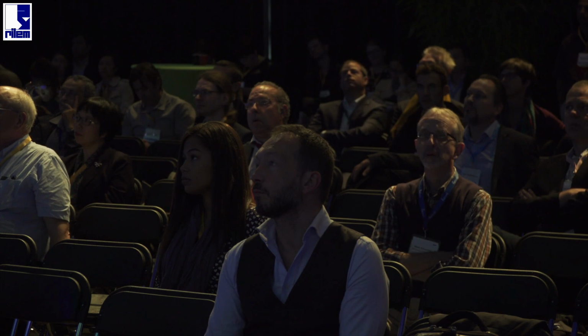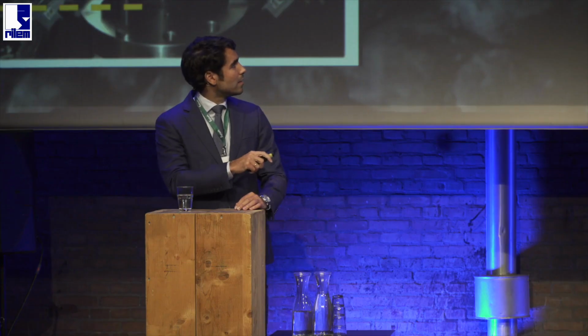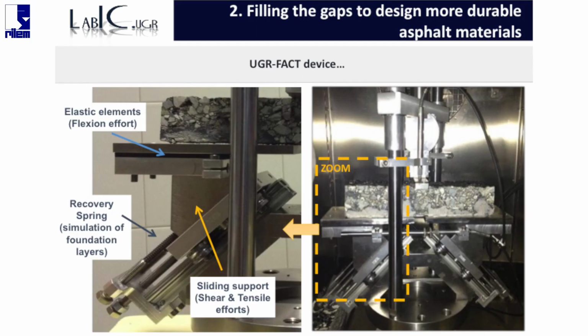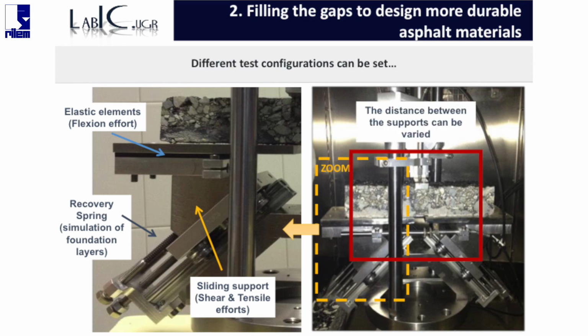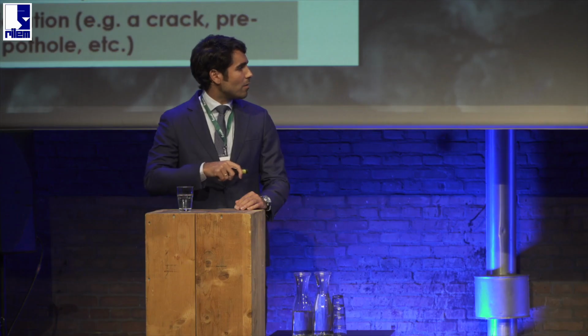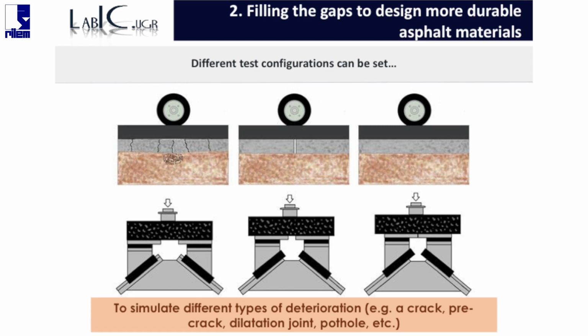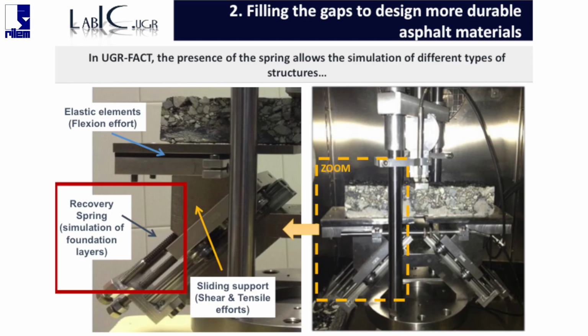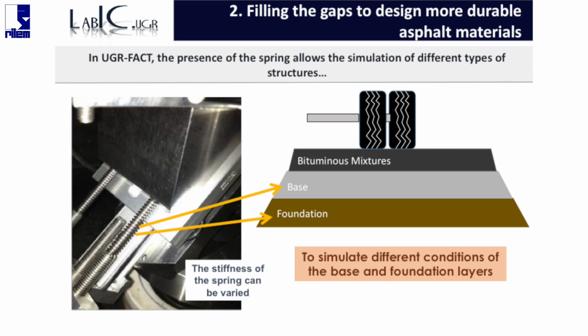So basically, this is an overview of the University of Granada fatigue asphalt cracking test. Here you can see the elastic elements, the recovery spring, and the sliding support. The test can have different types of configuration by varying the distances between the plates. So we can simulate different types of deterioration under the asphalt layer, like crack, pre-crack, dilatation joint, pothole, etc. In addition, the presence of the recovery spring allows us to simulate different types of base and foundation material.